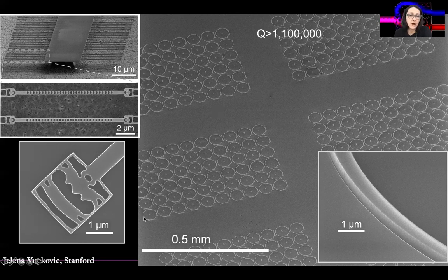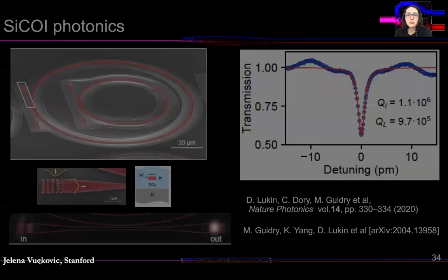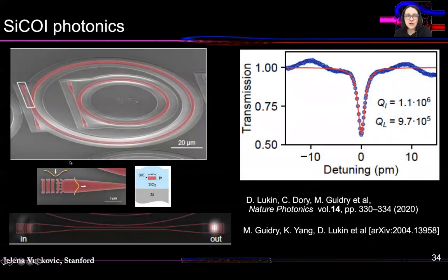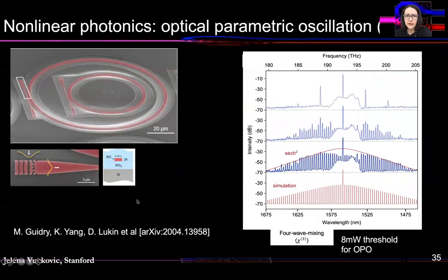We can actually implement optimized structures. We can inverse design couplers to resonators. These are measurements of 1.1 million Q factor in transmission through the resonator. And I already mentioned that silicon carbide has strong second order optical nonlinearity. We have seen measured effects of nonlinear interaction inside of these structures, efficient second harmonic generation. And also recently, we've shown optical parametric oscillation and demonstration of microcombs inside of these silicon carbide circuits with very low thresholds of only a few milliwatts.